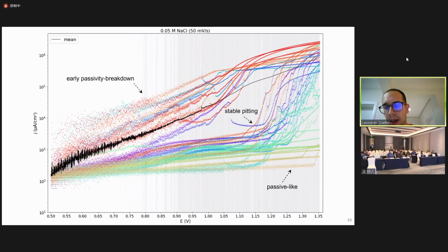As you can see, after that potential, we have increasing chances of getting stable pitting, but the distributions can be pretty wide because sometimes we have early passivity breakdown, etc. And after that, we realize that if you would like to deploy machine learning for pitting corrosion, the first critical step would be, in fact, to develop algorithms for estimating pitting potential, because in corrosion it's very important to define this point where we have localized corrosion. But where does this point lie? It really depends on the heterogeneities that we find on the surface and on the experimental conditions.